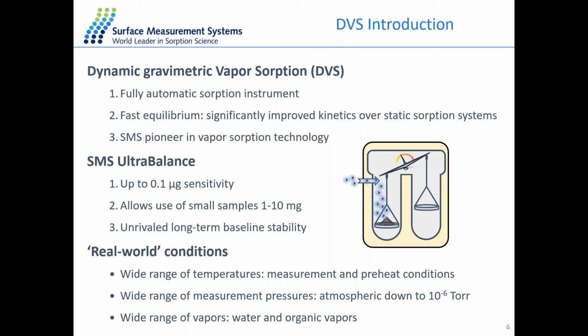And because we are using a small amount of sample and the resolution of the balance is very sensitive, we can achieve a much faster equilibrium compared to the static method. So a full sorption-desorption experiment could happen within just 2 or 3 days. And the measurement of the DVS technique can be under vacuum conditions or at ambient temperature and pressure. So we can simulate the conditions during the application of this product, and we can get more practical properties for the storage or the processing of this material.